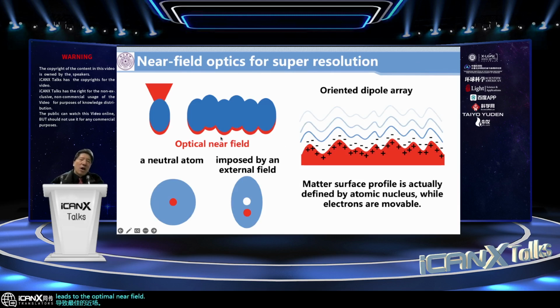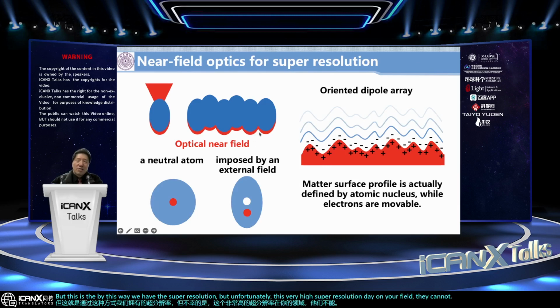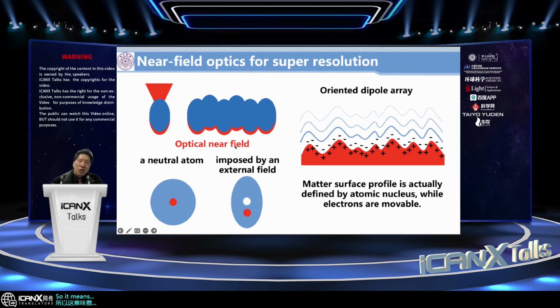This dipole leads to the optical near field. It means the optical near field can carry the high spatial frequency information exactly the same as the material surface. In this way we have the super resolution. But unfortunately, this very high super resolution is in the near field. It cannot propagate to the far field. So the price we pay for achieving the super resolution is that we lose the propagation property of the light field.